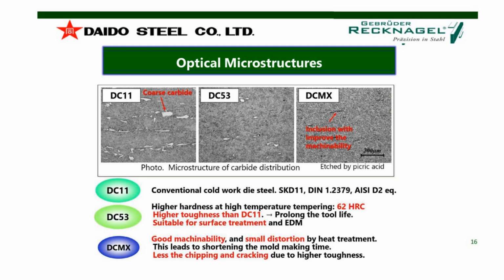microstructure in the matrix. But DCMX, of course, is not a powder steel. It's a conventional steel grade, but the microstructure is very close to a powder steel grade. And in this picture, you can see also the fine black linings, and those linings are the sulfur content. And as I mentioned, the sulfur content has no negative impact on the mechanical properties. It's just to bring up the machinability of DCMX.